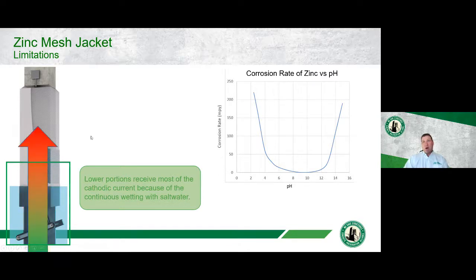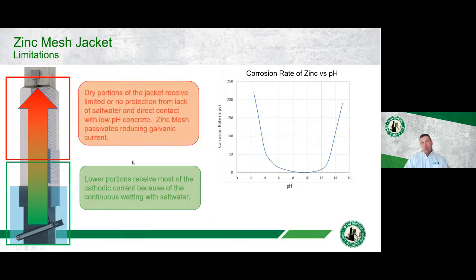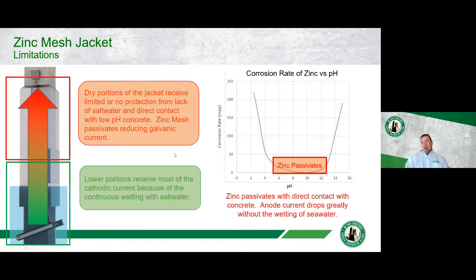But as we move further and further up on the pile, we end up getting into this drier zone. So in these drier zones, obviously there's limited availability of seawater, and without this seawater as an oxidizer, our zinc starts to passivate. And if you look over here at our corrosion rate chart, we can see the corrosion rate, or how much current zinc produces, versus pH. So if you look at concrete, it's typically going to be in this range here, older concrete on a marine structure. And if you look at it, zinc is going to passivate within this range. So that's what we have happening.